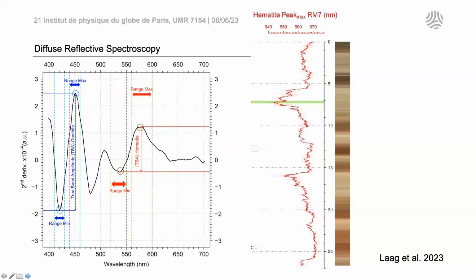And if you want an example of how true that is, this plot here is the wavelength of the peak position for the hematite. You can see that stratigraphically, that peak position in terms of wavelength varies quite significantly, and the variation is completely correlated to the stratigraphy. So this is telling you that it's shifting because of a mineralogical change of that hematite: grain size, maybe source or provenance difference, the pedogenic hematite with respect to incoming, more detrital hematite.